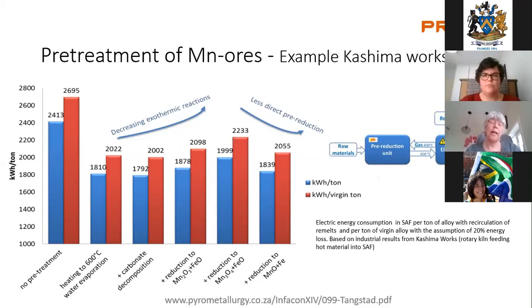metal. If we look to the left at the curves, we can see the effect of that on the consumption of electrical energy in the submerged arc furnace. This is only for the submerged arc furnace, not for the total system. The red bars are for the virgin ton, not including the remelt, and this has been recalculated to the blue one to be able to compare the theoretical calculation with the real achievement at Kashima Works. From the non-pretreated case on the left, they had nearly 2,700 kilowatt hours per ton.